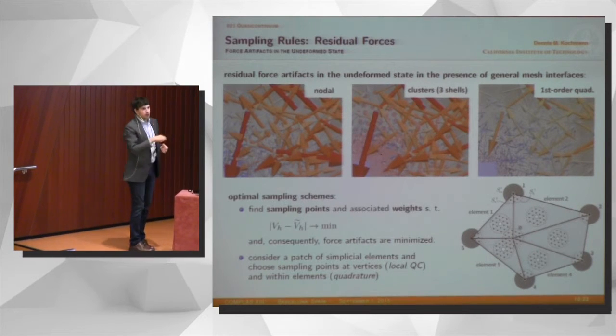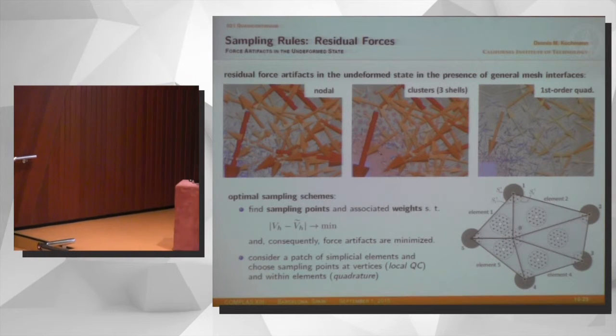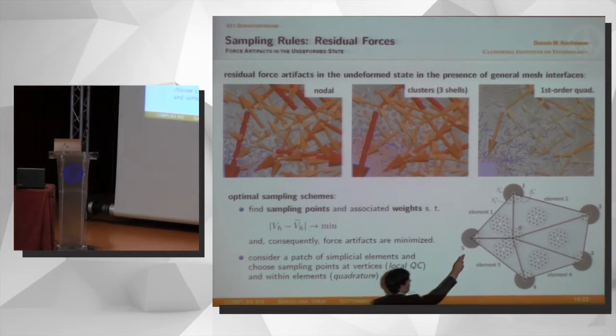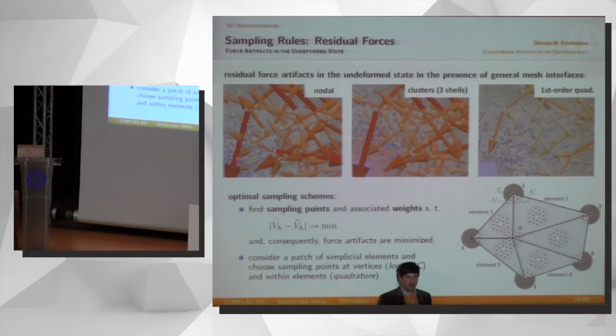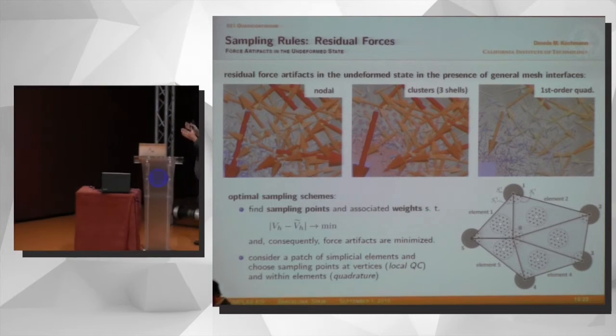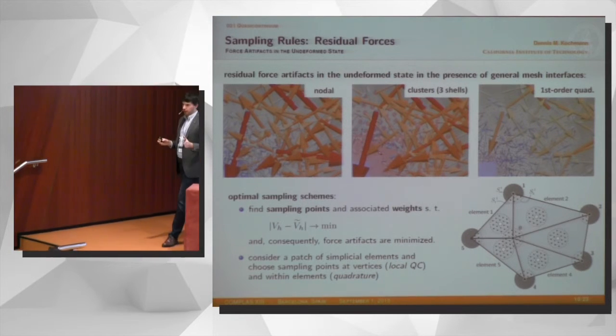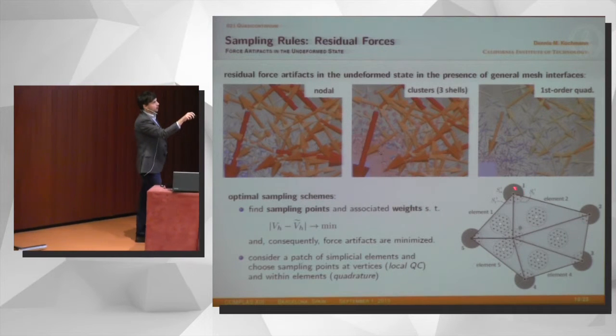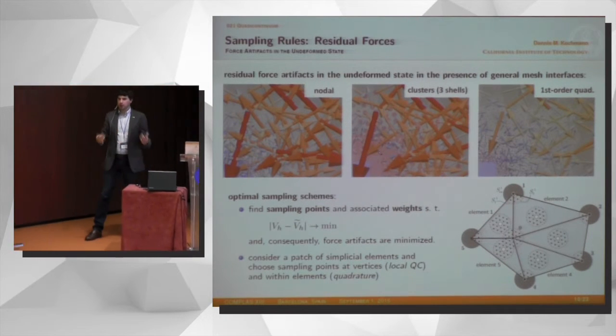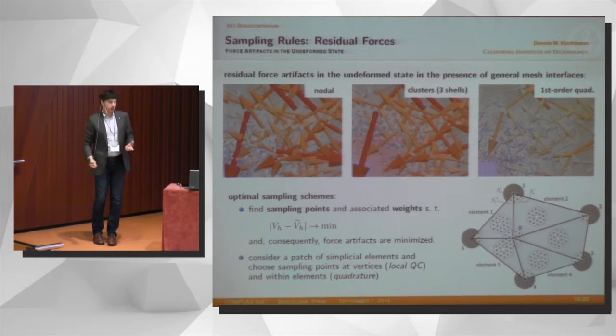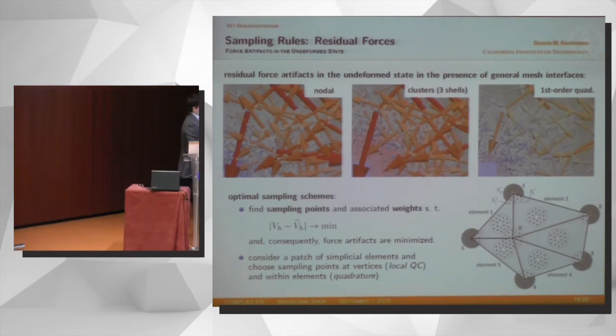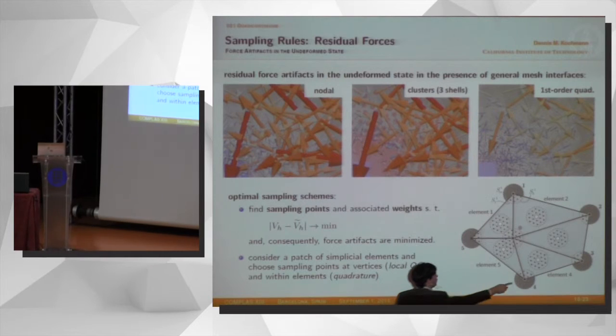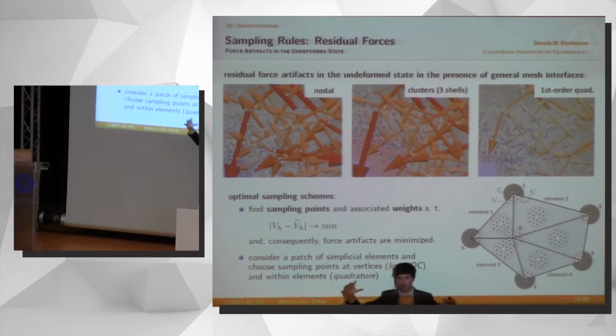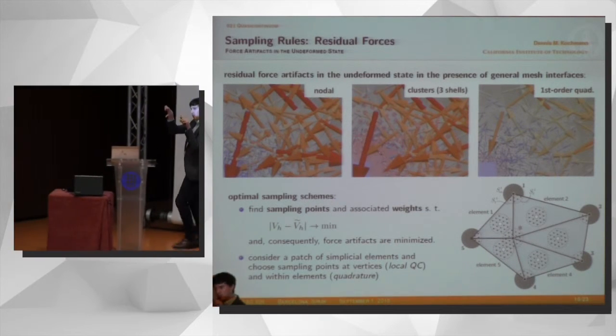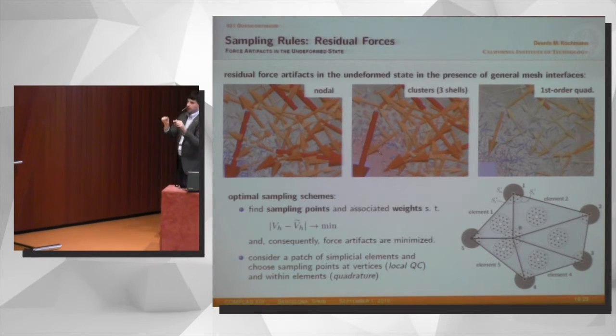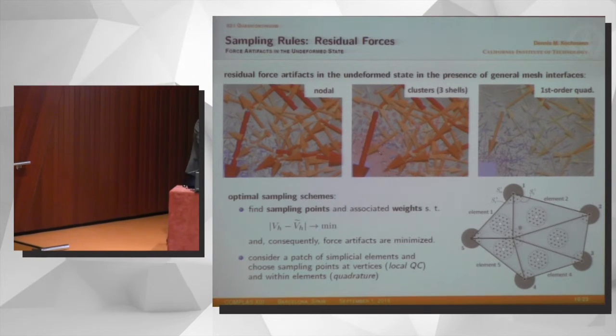So we can overcome this, and what we introduce is an optimal sampling scheme, where the idea is simply we use something like quadrature and finite elements. We use the nodes themselves. We compute their energy. And you have additional points on the inside, and you can actually find a way analytically to minimize the total energy error and to come up with the best way possible to compute the weights of these nodes such that you minimize the energy for arbitrary shapes of your elements. And we do specifically keep the nodes and additional points on the inside, because if we go down to full atomistics, we want the nodes to be in the simulation so that ultimately you're just doing atomistics. I'll show you this in the next slide.